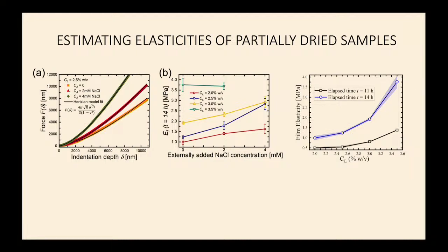As you increase the concentration of clay, and as you increase the age of the suspension, the measured elasticity in the micro indentation experiments increases, and as you increase the salt content in the sample, again the measured elasticity increases.